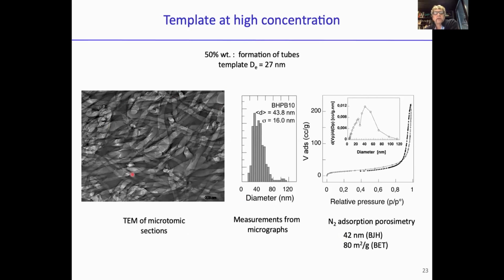Now, if we increase the concentration here, then this is the object that we got. We have the mesopores here. And from the TEM experiment, we can measure the diameters of the whiter area here. And this is the mean diameter of the pores that we get, and the polydispersity. So the template is 27 nanometers, and what we got is about 40 nanometers. And we also did nitrogen adsorption porosimetry to measure the diameter of the pores, and this is what we obtained. So we got a good agreement.